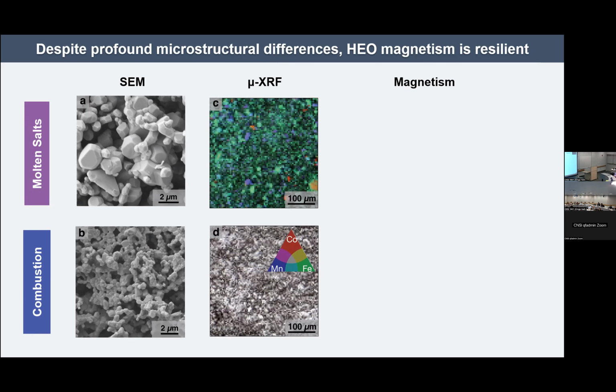The legend to understanding what you see here is shown in this triangle inset, where we can only plot 3 elements at once, but it's representative of what's going on. If you see a pixel that is blue, red, or green, it means there's an excess in the fluorescence signal of one of those elements. What we see with our molten salt sample is that it's pretty green everywhere. So there's an excess of iron.